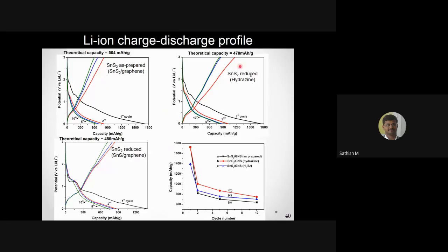Whereas this is the hydrazine reduced, you could see it is 900 plus. Okay, so even after 10 cycles, you could see it's almost close to 800 or 850. Whereas this one is reduced in hydrogen and argon atmosphere. This shows relatively poor performance, maybe here it's almost 700 or 750 milliampere hour per gram.